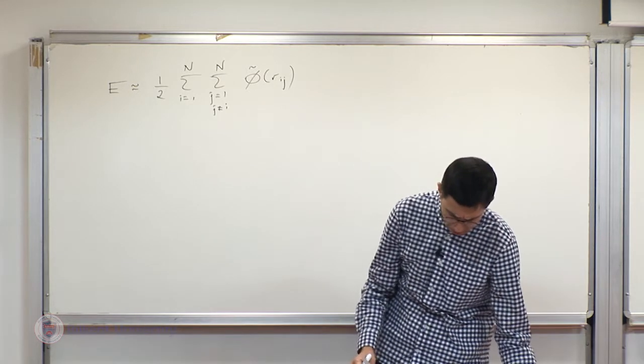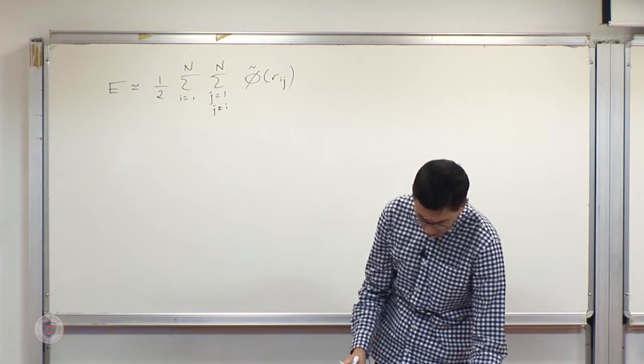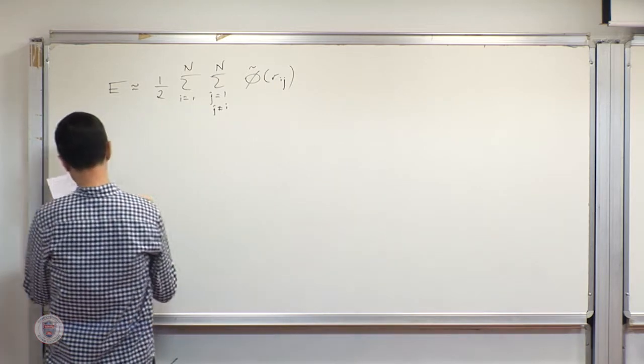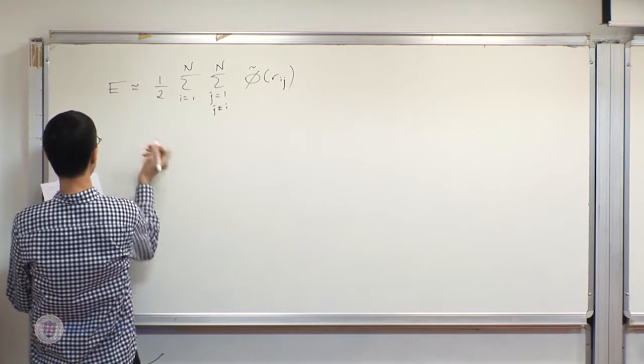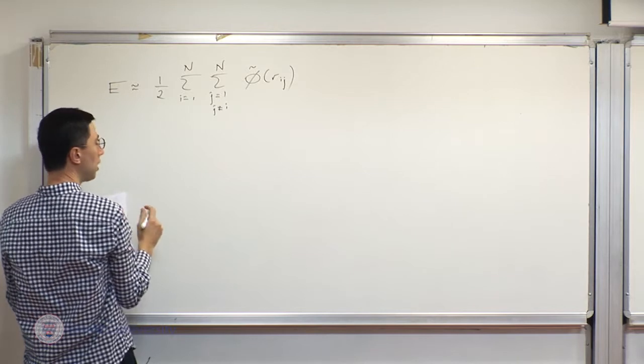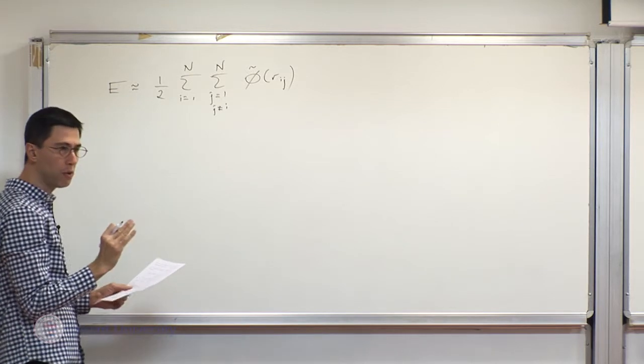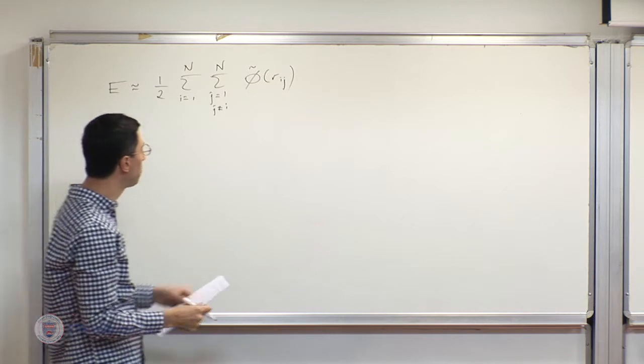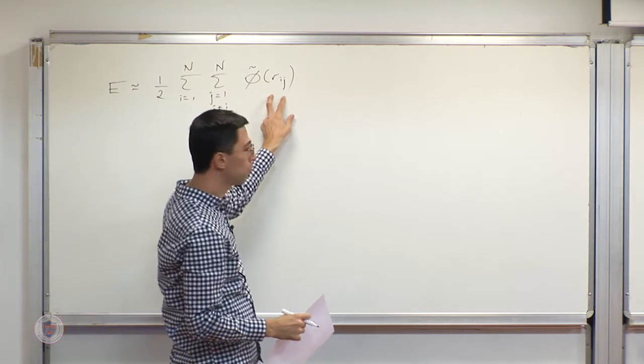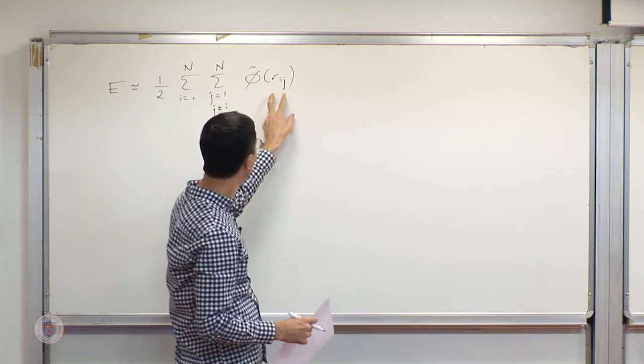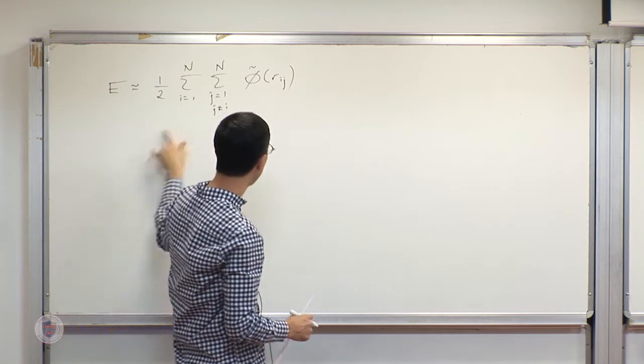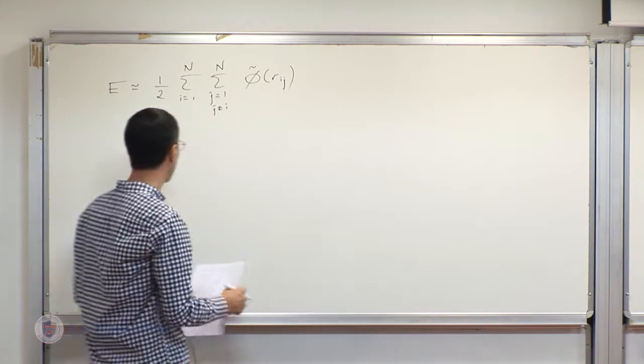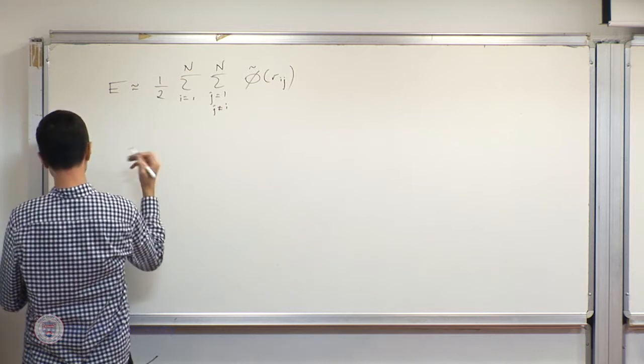We then made a transition to the concept of the overall energy of the system, and argued that if we invoke the so-called Cauchy-Born hypothesis, which maps the relative position vector between two atoms from the reference to the current configuration through the macroscopic deformation gradient at that point, the overall energy E is inherently a function of the macroscopic deformation gradient.